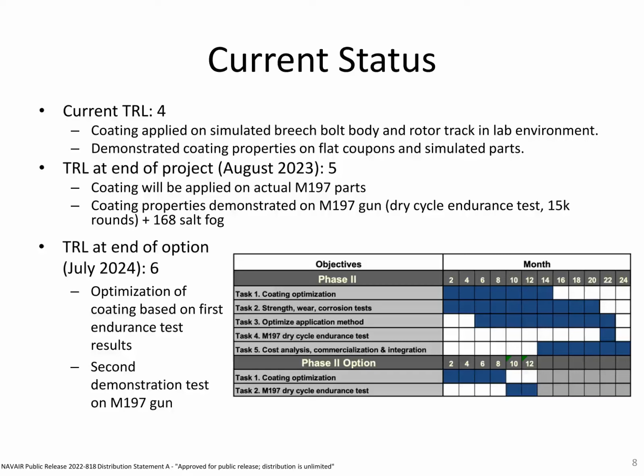We estimate that we're currently at TRL 4. We've demonstrated the coating on a simulated breech bolt body and rotor track in the lab environment. We can get protection up to 15,000 rounds. We're working on 30,000, that's the next goal. We've also demonstrated the coating properties like adhesion and corrosion protection and some of the other tribological properties that are of interest on flat coupons and the simulated parts. At the end of the project in August, we expect to be at TRL 5.